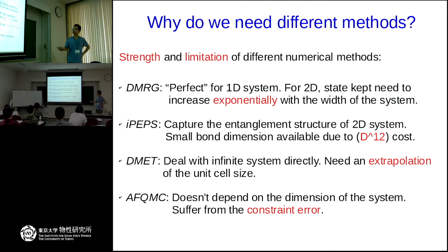And for iPEPS, as we learned in this morning's lecture, iPEPS can capture the entanglement entropy of the two-dimensional system, but due to the very large scaling with the bond dimension, at present the bond dimension that can be reached in this method is very limited. So with this limited bond dimension, we can't get a reliable scaling with the bond dimension D. For DMET, they deal with the infinite system directly, but we need to do an extrapolation of the unit cell size. For our QMC method, basically our calculation doesn't depend on the dimension of the system, but as I will show in next Monday's talk, we get rid of the sign problem, but we suffer from the constraint error.